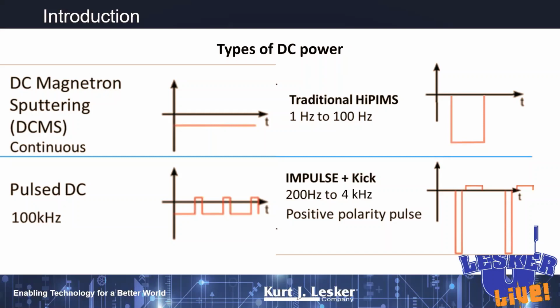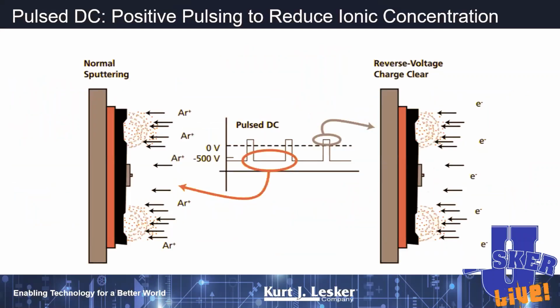So I'm going to just talk about sputtering power supplies for just a second. So just to show you some cartoons. So with pulse DC, again, we've got a big negative pulse here, which sends in our argon ions, or positively charged argon ions, some of which may actually impale themselves in the body of the target. And then we do a positive pulse here, which sends in a bunch of electrons, which mitigate any charges that may have tried to develop in our sputter target itself. And as I mentioned, in reactive sputtering, we may actually do some cleansing of any redeposited, let's say, nitride material that might start building up on the sputter track.